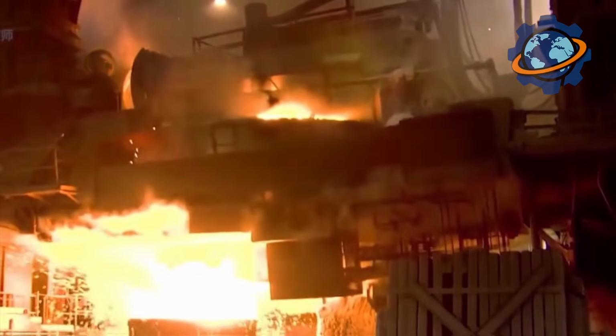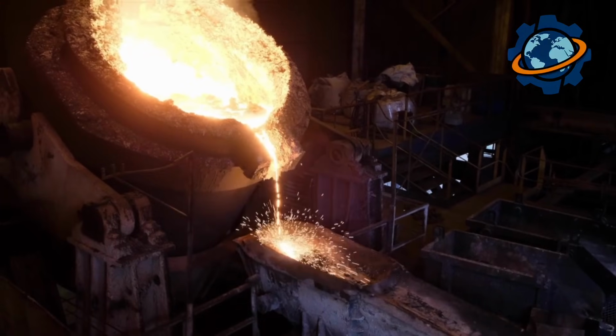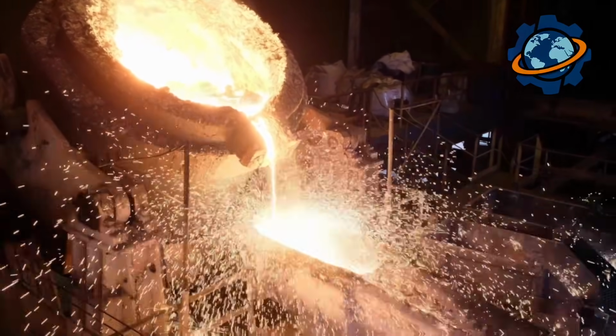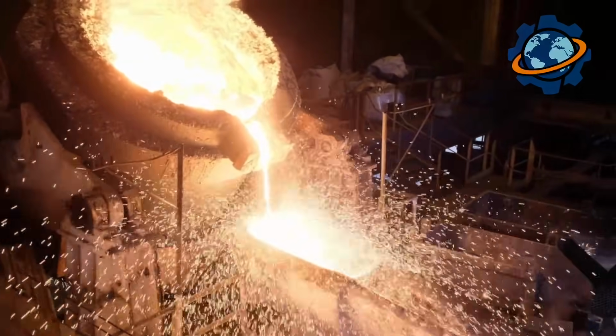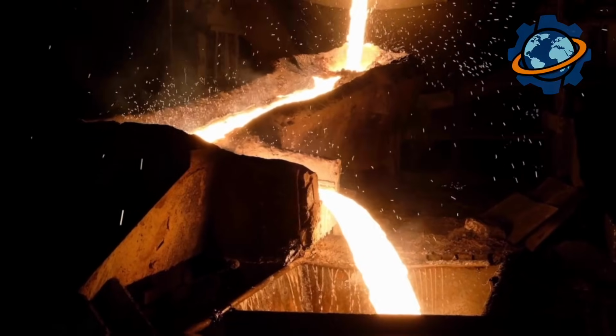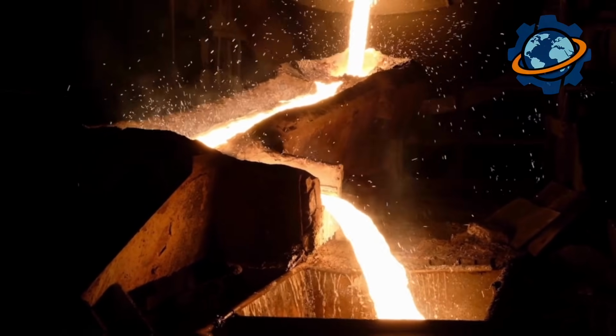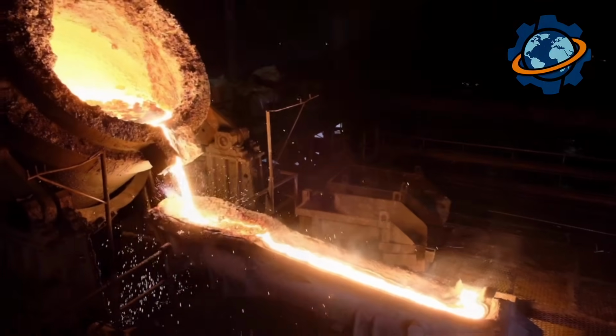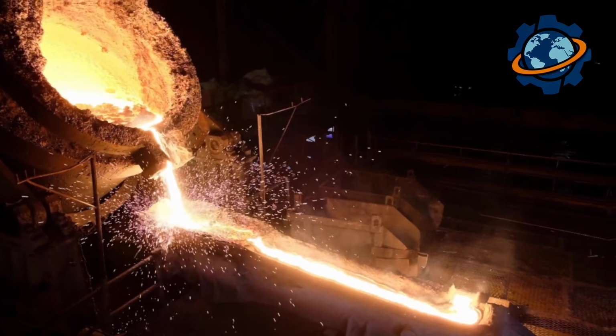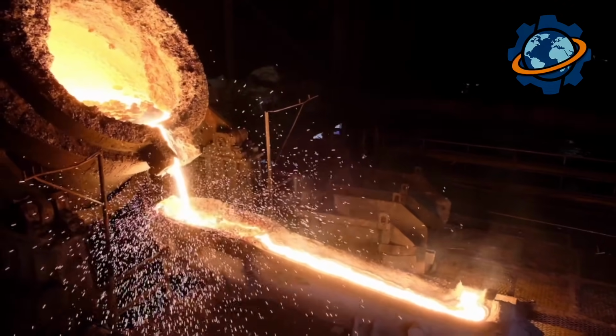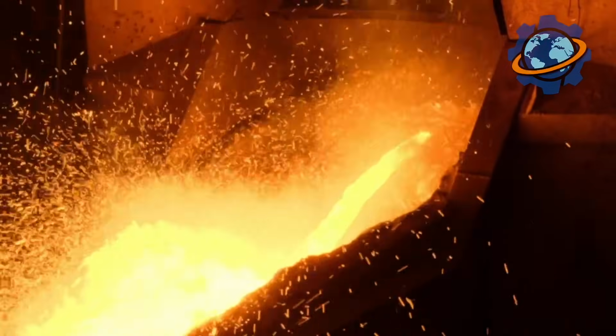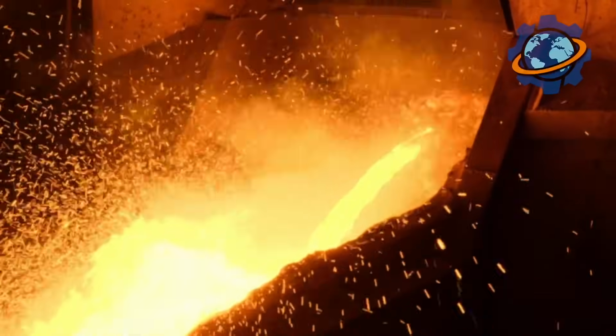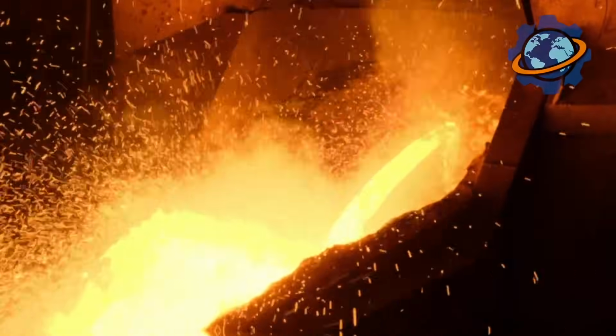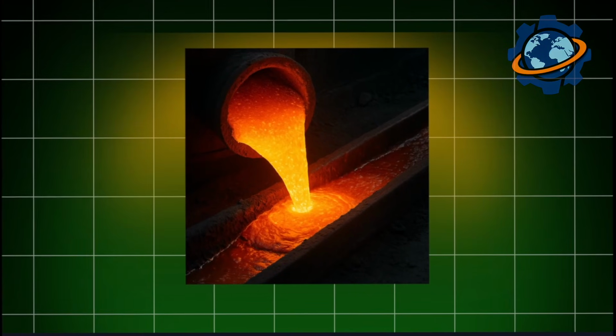First, continuous casting. Molten metal pours into a crystallizer, a water-cooled copper mold. Below, a solidifying blank emerges, a slab 8 inches thick, 6.5 feet wide. It glows red, surface temperature around 1,800 degrees Fahrenheit. Gas cutters slice the slab into 33-foot lengths. One slab weighs 25 tons.